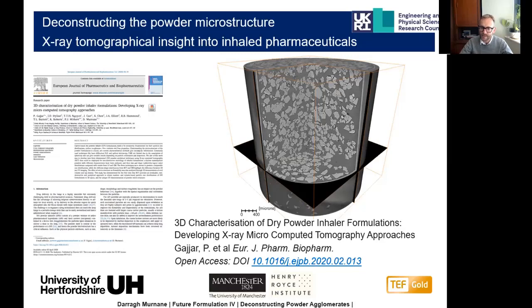We can start to see the spatial arrangements of the particles within these powder blends. And this is typical of the arrangement of powder within a capsule. We can see where the powder is located, we can see the density, we can see the porosity of this powder bed, and we can also start to pull out statistics like particle size distribution.